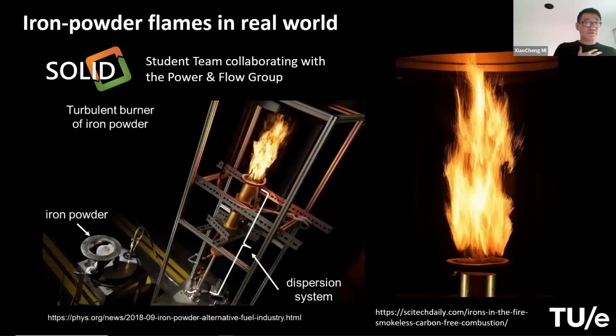And how about the iron powder flame in the real world? This picture shows one of the first iron powder burners that was developed by a student team at TU Eindhoven. What you are seeing here is not a 100% iron flame. It has methane mixed with iron powder, so it's a hybrid flame. You can see iron powder can be fed here, and then through this dispersion system, you can stabilize a turbulent flame on top of the burner.